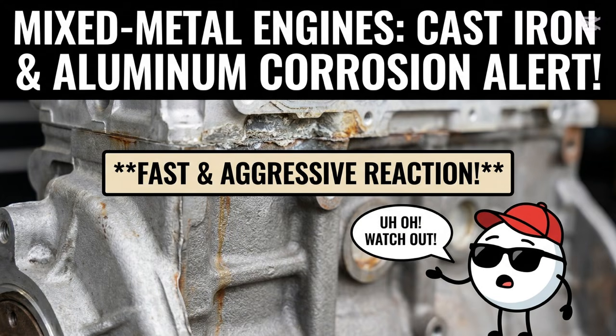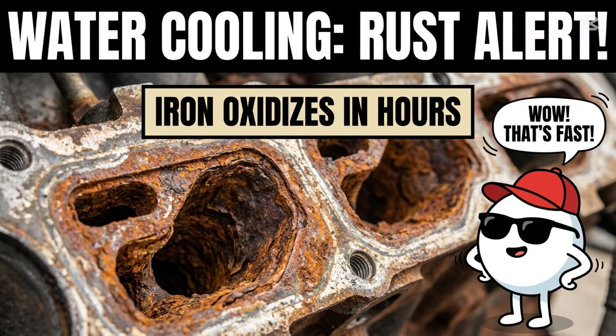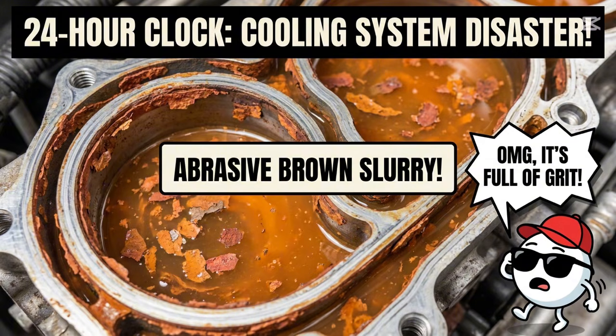If your vehicle happens to run a cast iron engine block paired with aluminum cylinder heads, a combination that's still extremely common in trucks and SUVs across the country, the reaction moves even faster and gets more aggressive. Iron exposed to hot, oxygenated water oxidizes essentially on contact, forming ferric oxide, plain old rust, within just a few hours of driving. As you continue on through that 24-hour window, that fresh rust scales off the cylinder wall cooling jackets and starts circulating through the entire system as an abrasive brown slurry.